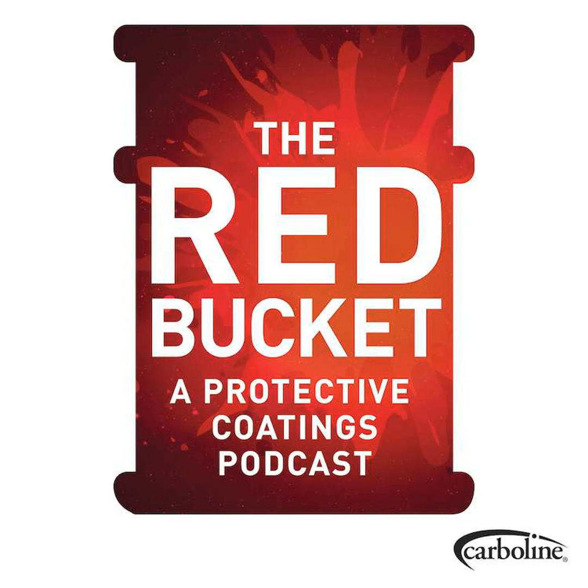Now, some of you may be saying, okay, well, paint erodes and degrades over time. This is true for most organic coating systems. So think about epoxies, urethanes. They will break down over time with exposure to UV light. In the case of a silicate system, these materials are inorganic and they do not break down in UV light.